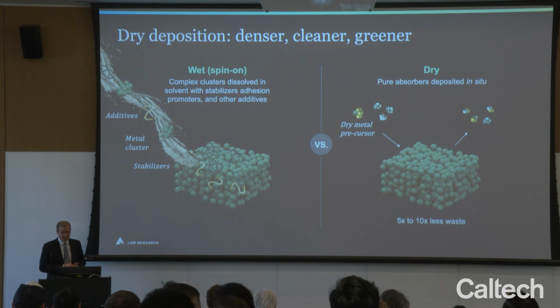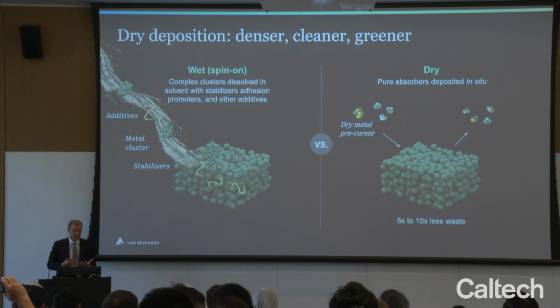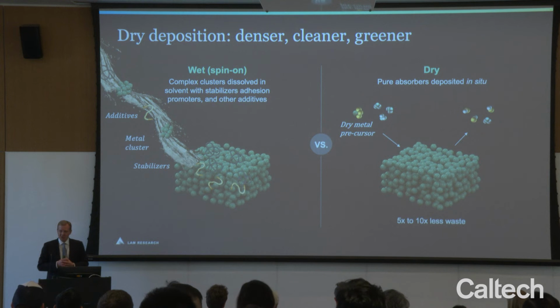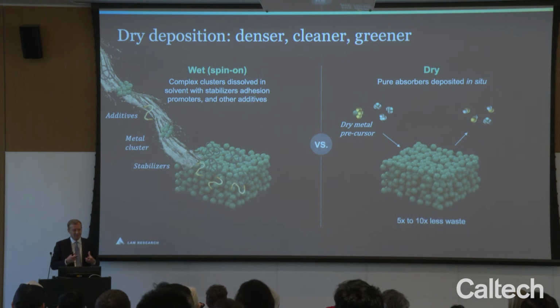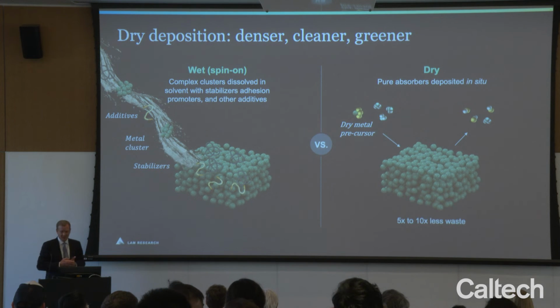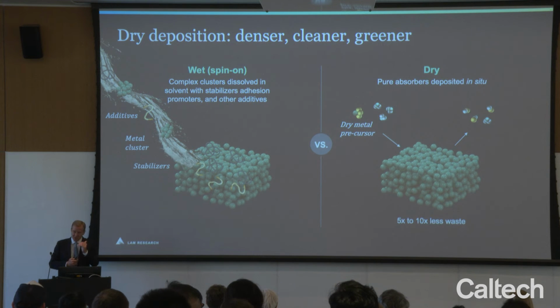The second change we're making is the method by which these photosensitive materials are deposited. In the industry, we're fast to change on certain things and very slow to change on others. For the last 4 or 5 decades, basically photoresists have been deposited by spinning material onto a wafer. But to do so, you have to add a lot of extra chemicals to the mix. You need adhesion promoters, you need stabilizers. And as you start to get to this atomic scale, those extra additives can lead to degraded film uniformity, degraded film pattern fidelity, and also increased defectivity. And so our dry process helps us to deposit a very pure, very compact matrix that ultimately allows us to print a very precise circuit pattern.